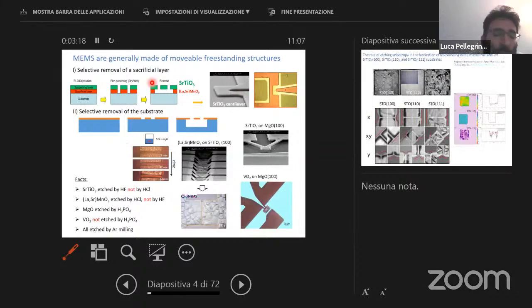So the basic structure for these oxide MEMS is the freestanding element, and we have two different routes to fabricate this freestanding element. One is to deposit a sacrificial layer, then do patterning by photolithography, and release the freestanding element by selective acids. I will show you an example, and we do this by pulsed laser deposition.